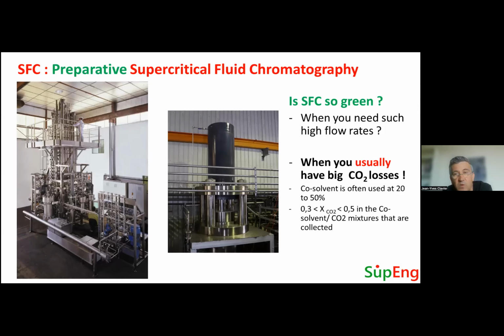When you use chromatography with CO2, what is observed is that actually we use a lot of co-solvent to make it the right elution solvent for chromatography. And it is quite frequent that we use co-solvent up to 20 or 50%. And here comes another drawback of supercritical chromatography at preparative scale, because like in extraction, we have to collect the product. And here we collect the product diluted in the co-solvent. When you look at thermodynamic equilibrium in the fractions collected in the liquid phase, you get a lot of CO2 that is dissolved in these liquid solvents. When looking, for instance, at ethanol at 50 bar, you get between 30 to 50% of CO2 dissolved in liquid ethanol.